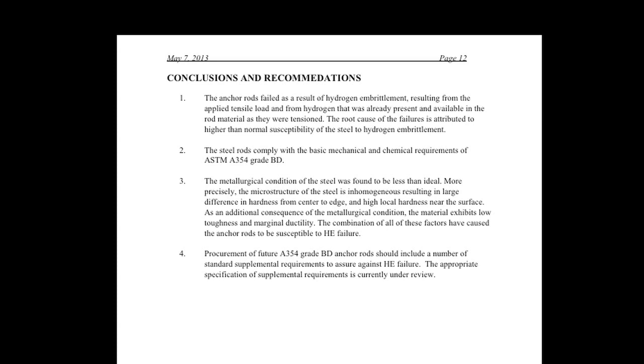On that page, the first conclusion is that the anchor rods failed as a result of hydrogen embrittlement, resulting from the applied tensile load and from hydrogen that was already present and available in the rod material as they were tensioned. The root cause of the failures is attributed to higher than normal susceptibility of the steel to hydrogen embrittlement.